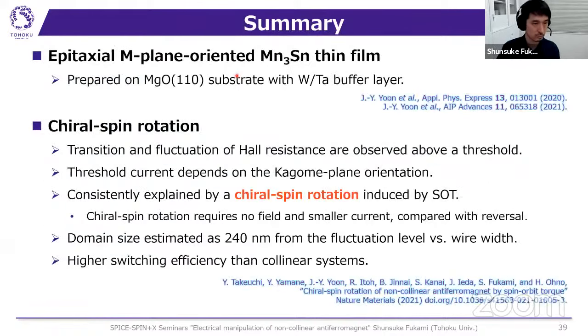Okay, so with that, let me summarize my talk. I first described the epitaxial M-plane oriented manganese tin thin films, and we prepared the epitaxial systems on the MgO substrate with tungsten and tantalum buffer layers. And then I described the chiral spin rotations. I showed that the Hall resistance transits and fluctuates above a threshold current density, and the threshold current depends on the Kagome plane orientations. These results can be consistently explained by the chiral spin rotation induced by the spin orbit torque.